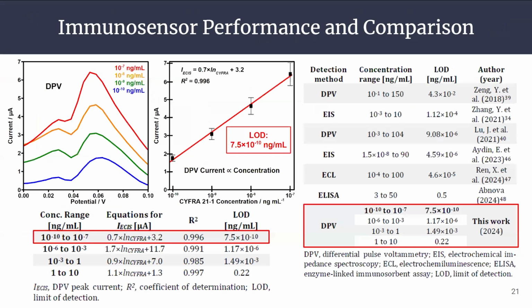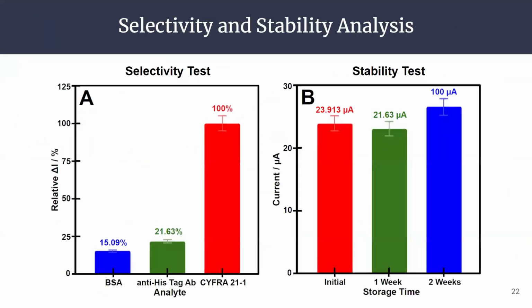Finally, the immunosensor performance was analyzed by differential pulse voltammetry in 4 consecutive concentration ranges of CYFRA. We obtained linear regression models for each range, which allowed us to accurately predict the CYFRA concentration. A limit of detection of 7.5 times 10 to the minus 10 nanograms per ml was achieved, being the lowest LOD reported for any CYFRA detection technology.